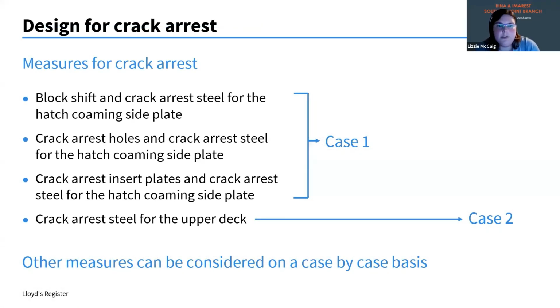IACS basically suggests measures that you can use to try and reduce the risk of brittle fracture. The first approach you can take is to design for crack arrest. So you assume that a crack will initiate and propagate, but something about the design of your ship is going to prevent that crack from leading to the loss of the ship. Its propagation, its growth, will be halted by something. And that something could be various different mechanical measures.